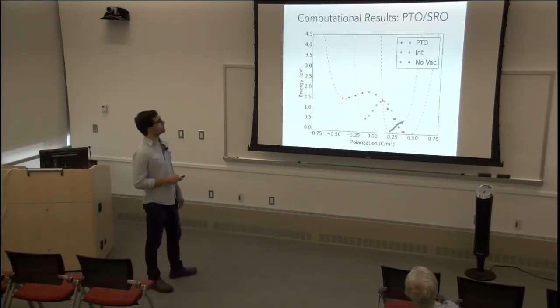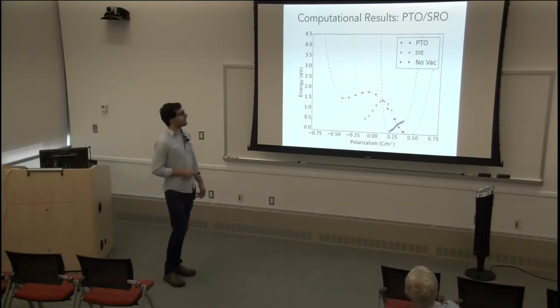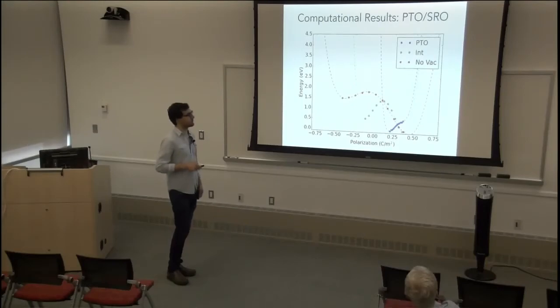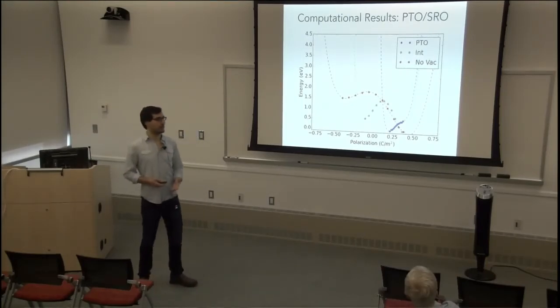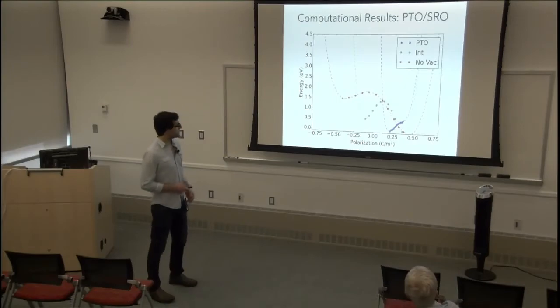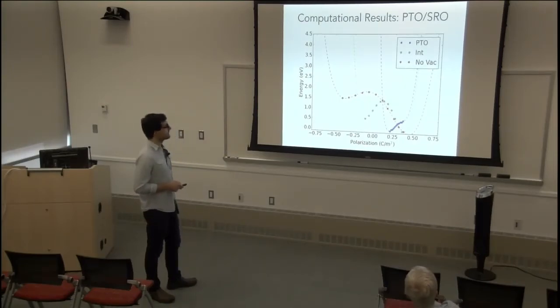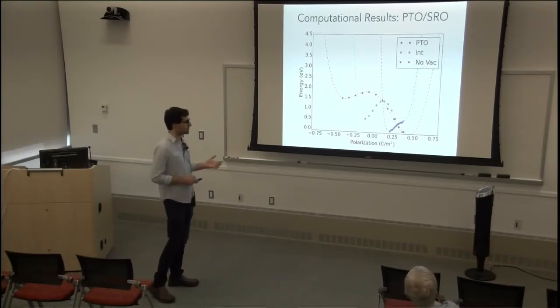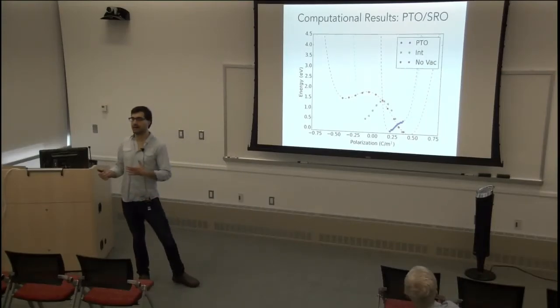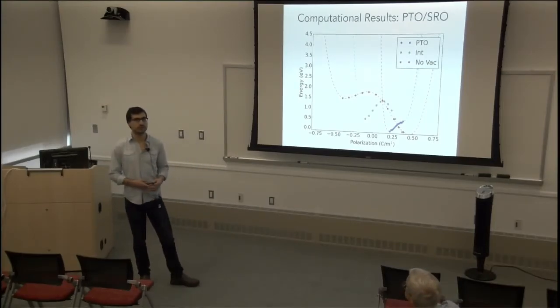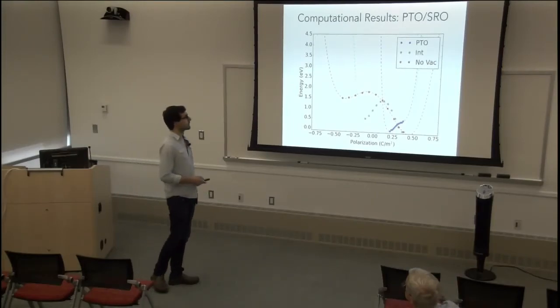And another thing that you notice is for lead titanate, you have this really weird double well potential. It almost seems like a single well. And this is kind of where we want cross-validation, because this basically tells us, okay, if you have a divacancy in the lead titanate, you end up with a single well. Experimentally, we don't actually see that. And so what we know is the cause of this is due to the limitations of our simulations, because we're constrained in size to make sure the simulation doesn't take forever to run.